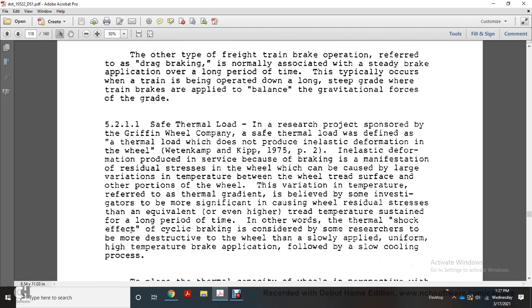Safe thermal load, in a research project sponsored by the Griffin Wheel Company, was defined as the thermal load which does not produce inelastic deformation in the wheel. An elastic deformation produced in the surface because of braking is a manifestation of residual stress, and it can be caused by a large variation of temperature between the wheel tread surface and other portions of the wheel. The variation of the temperature is referred to as a thermal gradient.